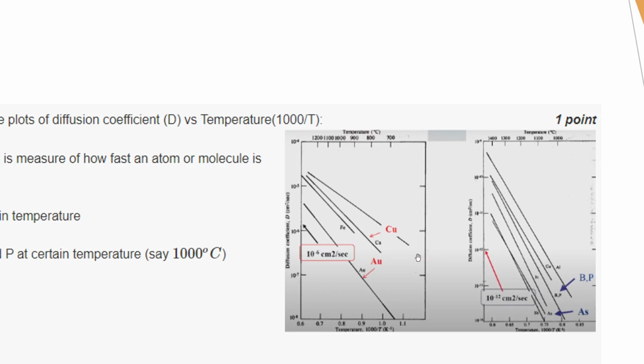So, because of that these are straight lines, and this is true for most of the materials. We can see that for gold and copper the diffusion coefficient is of the order of 10 power minus 6 centimeter square per second, and for boron, phosphorus, arsenic it is somewhere around 10 power minus 12. So it is higher in the case of copper and gold. That is what we expect, right. Because copper and gold are metals, they will occupy the interstitial sites, and interstitial diffusion is faster. So, the diffusion coefficient is higher.